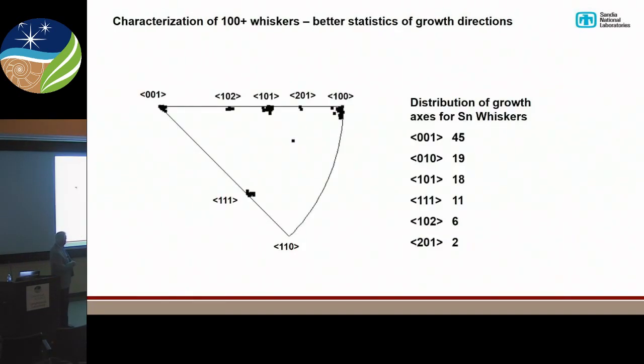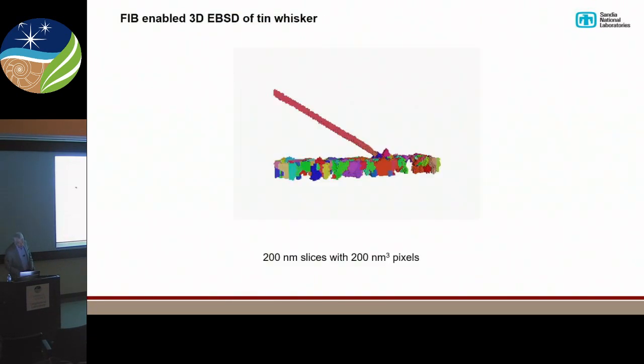There's a plot. This is an inverse pole figure. And these are the various growth directions for about 100 whiskers that we characterized using EBSD. So we can go through and we can actually figure out which ones have the 001 growth direction, because tin's tetragonal, so it's not the same as the 010. And you go through that and so forth. So quite powerful.